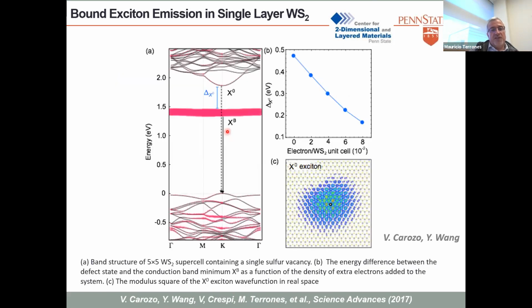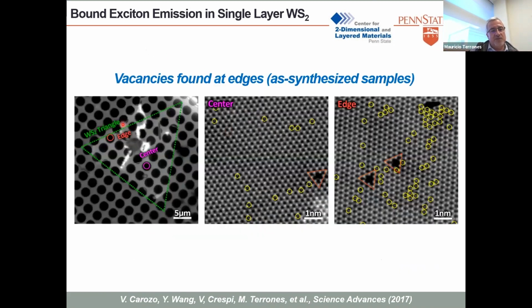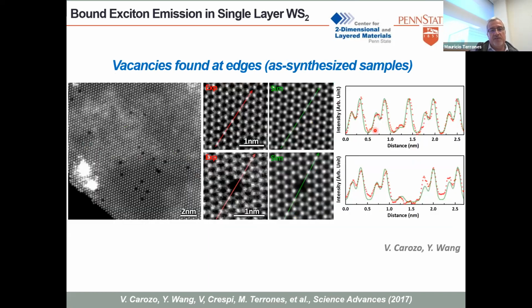So what we did is we did the Raman on the same triangle, and the microscopy on the same triangle. For instance, you transfer this tungsten disulfide triangle onto a TEM grid, and then you do spectroscopy here and microscopy in the same regions. Then you can look at the edge, and you can look at the center. The center has a few vacancies. These are the sulfur vacancies. But the edge always has more sulfur vacancies. So we then quantify the sulfur vacancies, right?